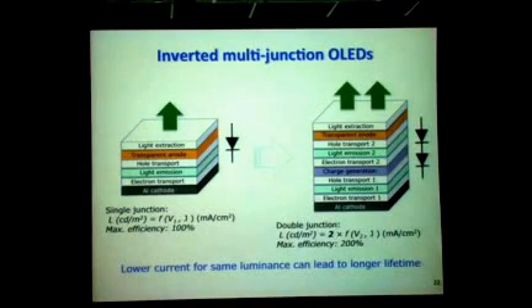The power efficacy is going to be similar, but the current efficacy, the number of candelas emitted per unit current, is going to be double. The other advantage of stacked geometry like this is that for the same luminance, because you get emission from two layers, you can run these devices at lower current, and that generally leads to longer lifetime, because the lifetime of these devices usually correlates with the number of electrons flowing through these structures.